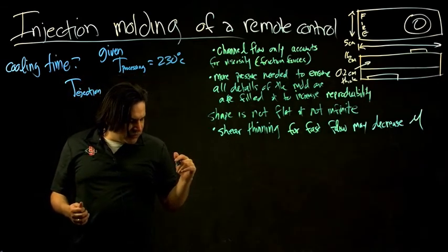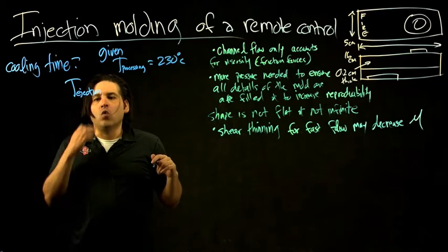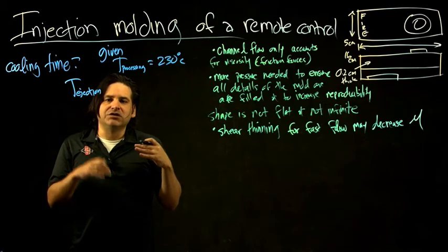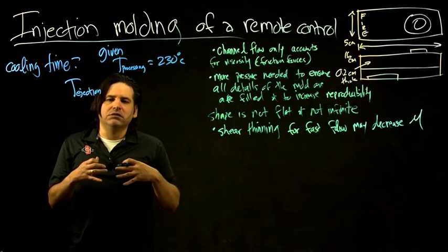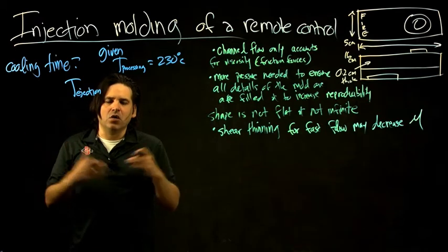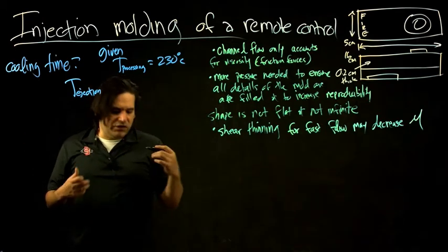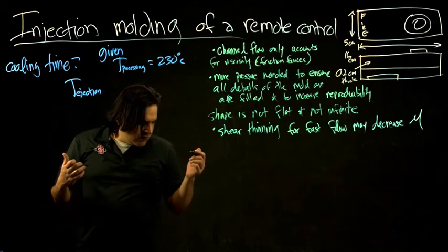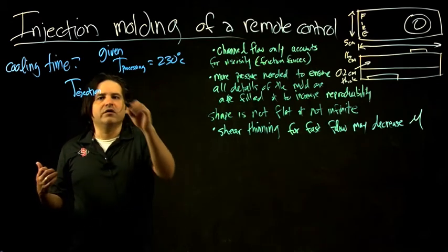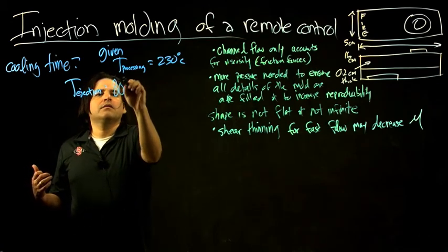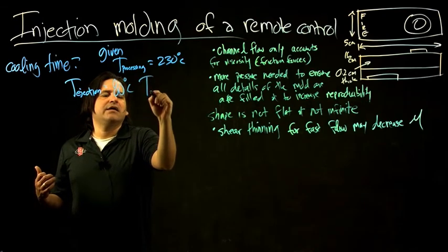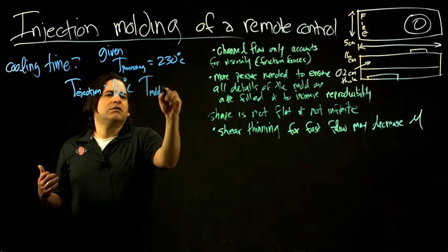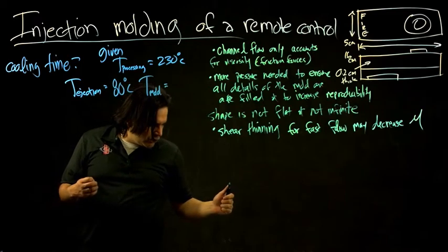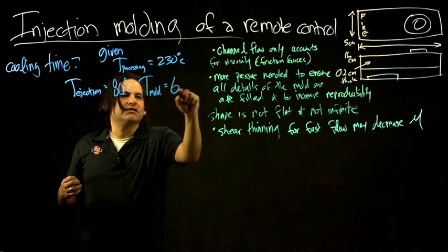Why? Because if it's too warm, the material is not solid, and it will either just be liquid or it will deform. The ejection process will change the shape if it's not hard enough. Let's say that is 80 Celsius, and the mold that we keep at a controlled temperature is 60 degrees Celsius.